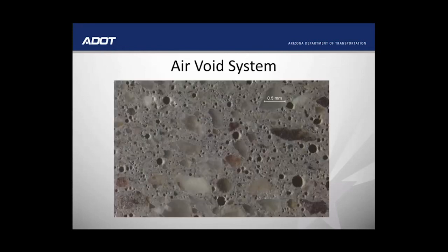Also of note for durability is the air void system. Notice the scale of 0.5 millimeter. These are not coarse aggregate in the photo. These are very small granules of sand. Notice the relative size and distribution of the air bubbles. This is a characteristic of durable air-entrained concrete by ACI recommendations.